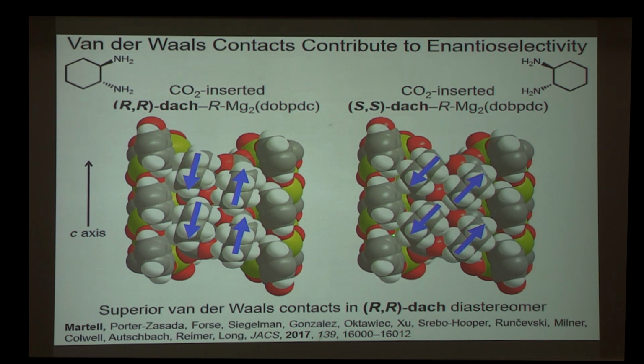In this diastereomer, this angle leads to less favorable van der Waals contacts. So again, this is suggesting that this diastereomer is more stable. So overall, there are a large number of non-covalent interactions leading to a high degree of enantioselectivity. And the role of the MOF is to interact with the bound guest molecules, but also to serve as a chiral three-dimensional channel to suitably orient the guest molecules to interact with each other.